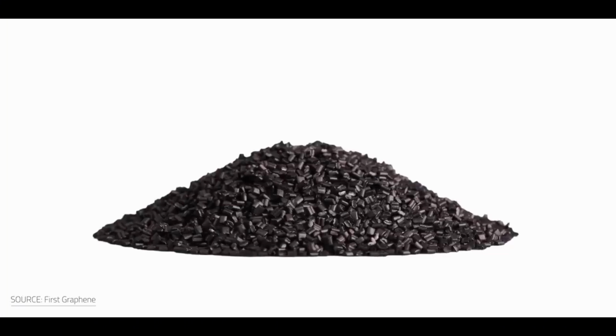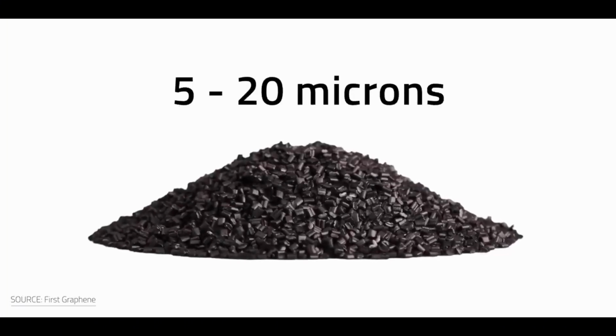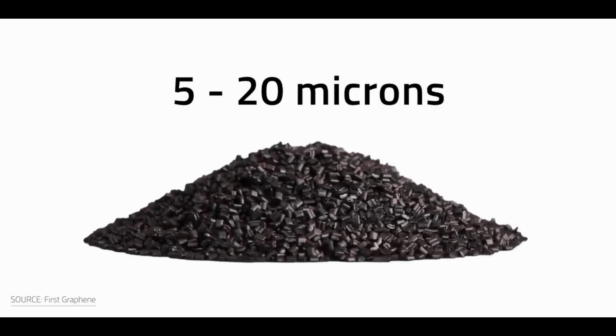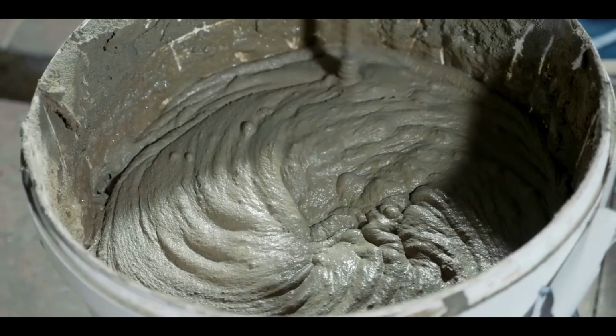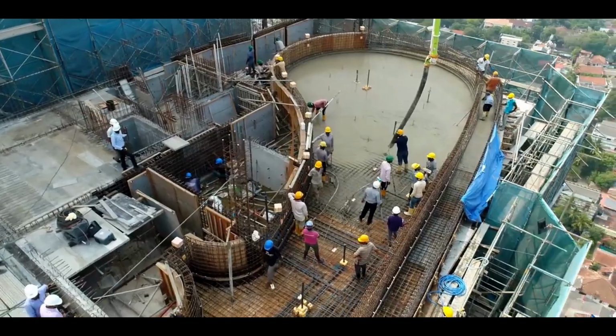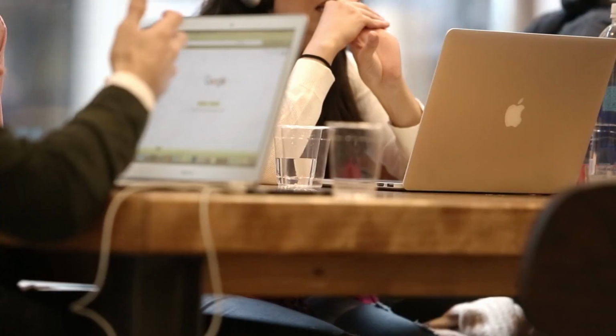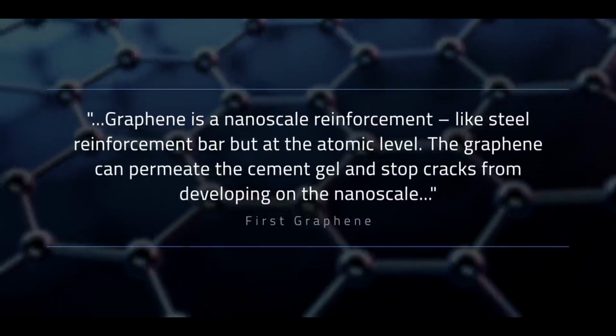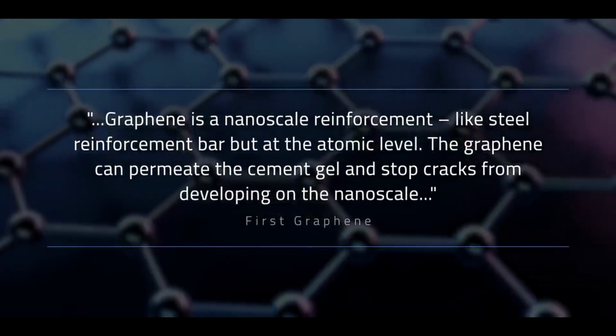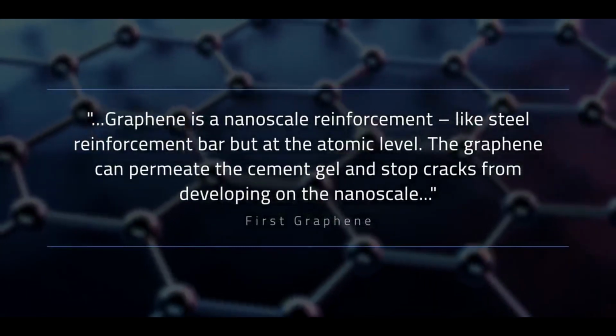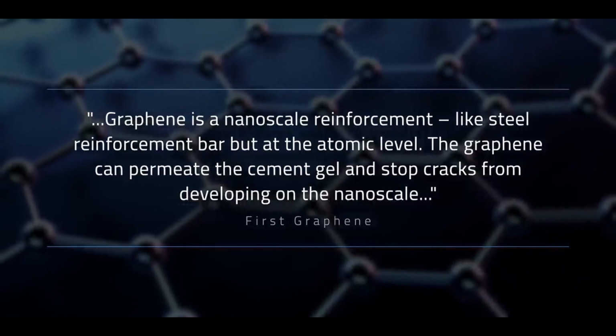They can produce graphene platelets with sizes between 5 and 20 microns, which can then be easily dispersed into materials like concrete, adding just a small amount of their graphene product, as low as 0.01% of the total concrete mix, to concrete improves tensile and compressive strength, also reducing weight and the chances of cracking. The company explained how these improvements happen. Graphene is a nanoscale reinforcement, like steel reinforcement bar, but at the atomic level. The graphene can permeate the cement gel and stop cracks from developing on the nanoscale.